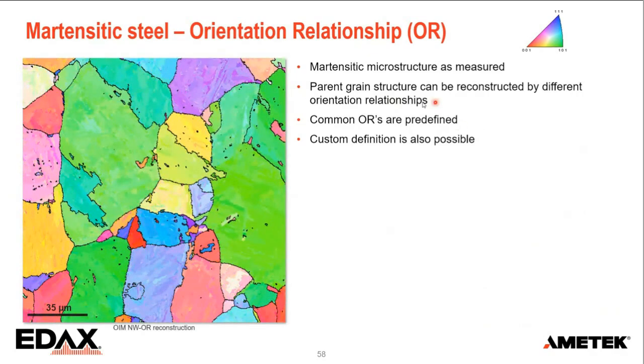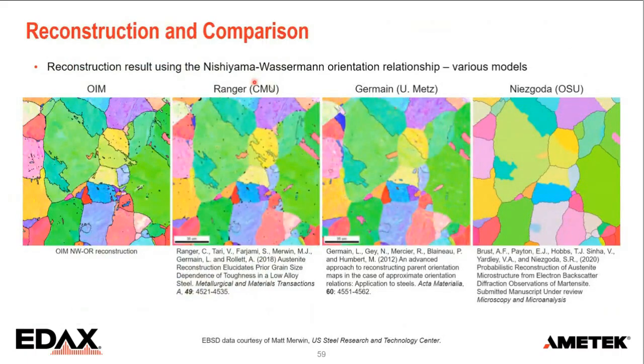And we can reconstruct this parent structure by the different orientation relationships. The most common ones are predefined, but you can also make your own if you want to. And we have verified this by comparing the same data set with different models, just to see what the variation in the different approaches is. And as you can see, they are all very, very similar. So we are quite confident that you get good quality reconstructions with the tool that we have implemented.